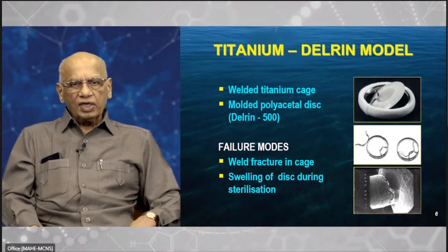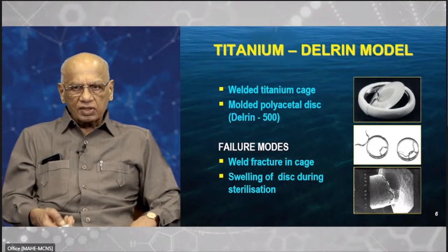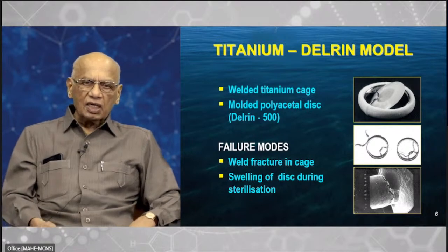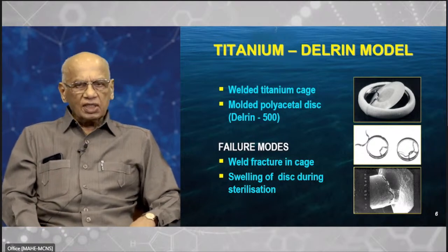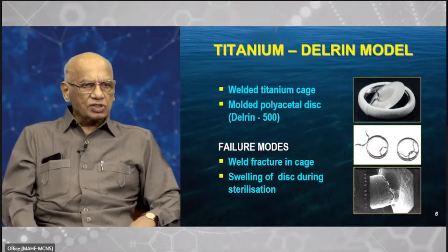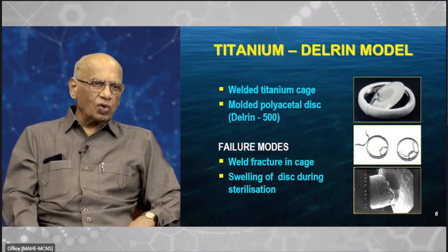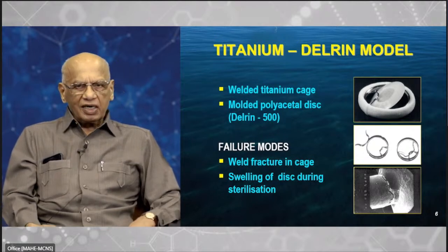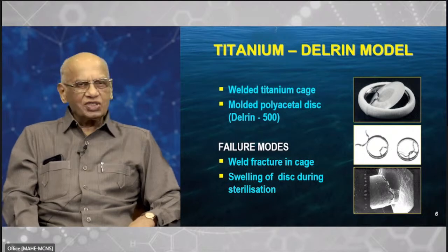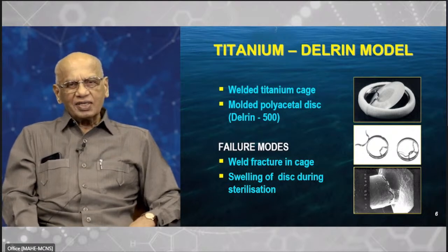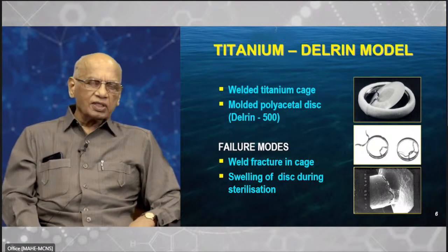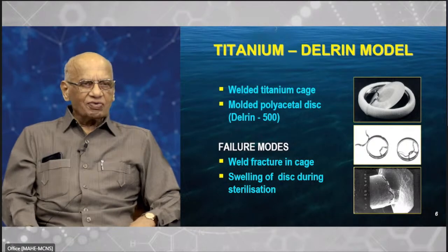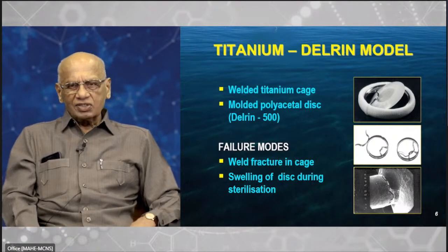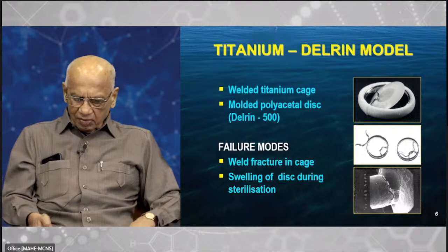When we put it in the wear tester, the titanium cage you have seen there, and you can see the polyacetal disc. Polyacetal is a very, very cheap plastic. When we asked DuPont for a pro forma invoice for 1 kilogram of this DELRIN, they sent us a packet of 10 kilograms free because it was so cheap. I remember that. The first valve, which you see at the top, when we put it in the wear tester, we are talking about millions of cycles, but after some 100,000, this is what happened.